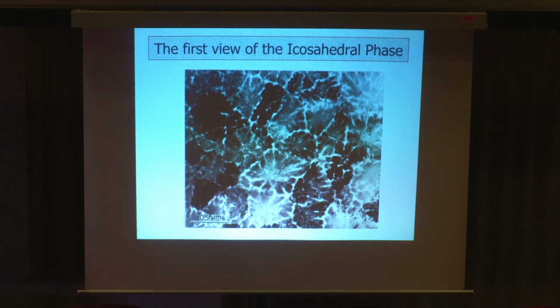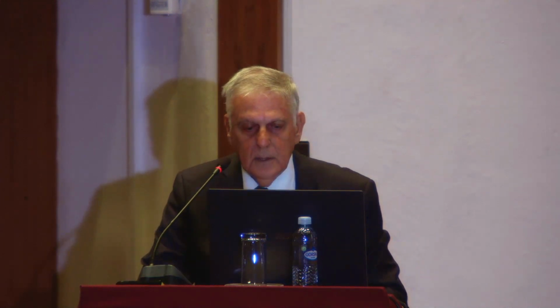Bright field image means taking the image with a transmitted beam. If the crystal is pitch black, it means that the transmitted beam has almost no intensity. So where did the electron go? To the diffraction. So this crystal diffracts heavily, so heavily that the crystal is pitch black, and I have never seen such a black crystal before in my life, and I was very experienced in electron microscopy. And I say, wow, that's interesting. So I take a diffraction pattern from that black crystal only, and this is what I see.